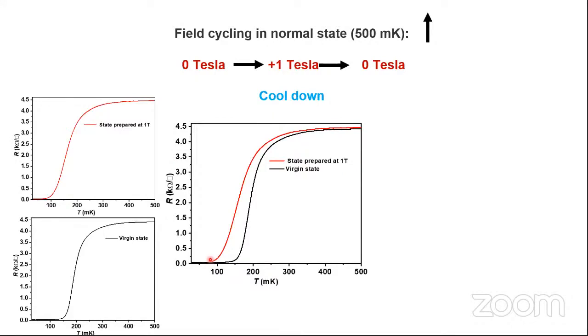normal state. So in this case, I want to mention that as an experimentalist, one of the suspects is the magnet itself. If by ramping the magnet up to 1 Tesla I have a remanence in the magnet, we have done experiments to very carefully rule it out. In fact, we have seen data that I'm not going to present today unless a question is asked, that we did get dependence of the superconducting properties of the interface. And we found that the remanence field that we measure is also dependent on the gate voltage that we apply.